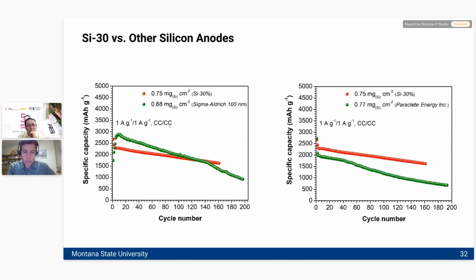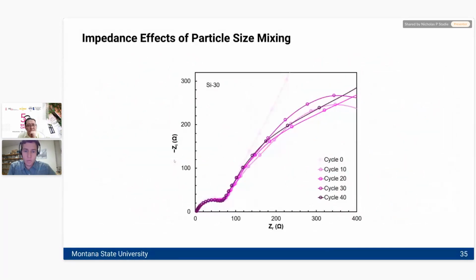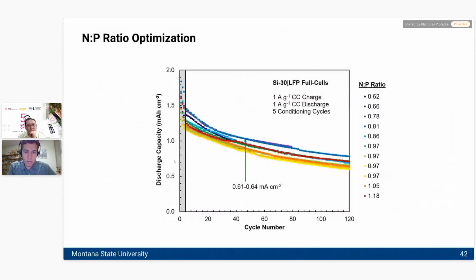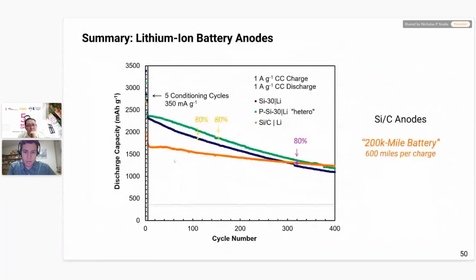All of the anodes that I showed you, except for in one slide, were pure silicon. So this is a good example here. This red material, this is what we call Si30. It's 30% nano, 70% micron. This is a pure silicon electrode, no carbon. It's got some binder inside. We use a cellulose type binder, so it's an aqueous dispersion, but there's no carbon content in these materials at all.